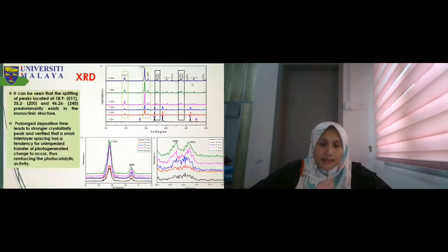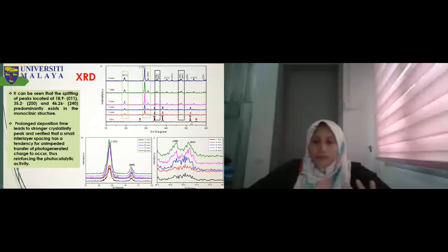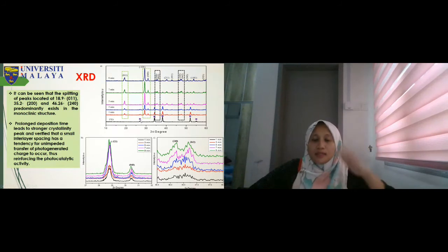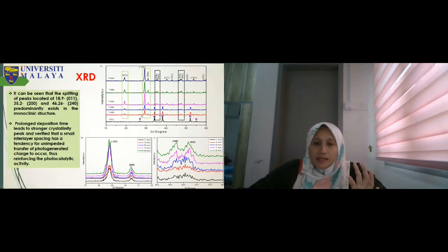Okay, this is for the XRD. This is important because we want to check the crystallinity of our material after deposition on the FTO surface. This graph represents the monoclinic bismuth vanadate. Here, I put the FTO. The FTO has a major peak. After we deposit, from the 1 minute sample, the FTO peak will decrease because the thickness of the bismuth vanadate is increasing, and we can observe that after we increase the time of the electrodeposition method, the crystallinity in the XRD analysis will also increase.